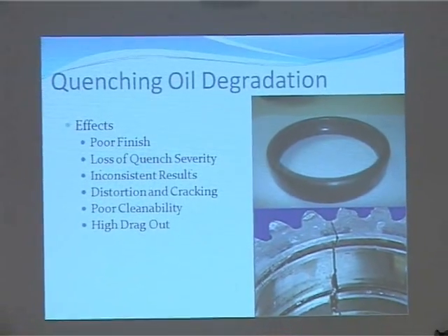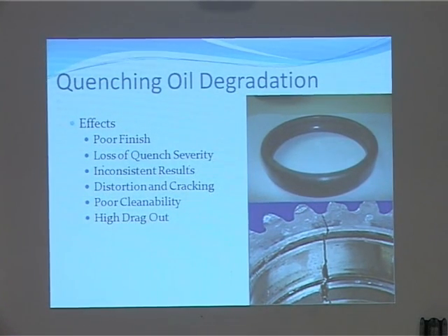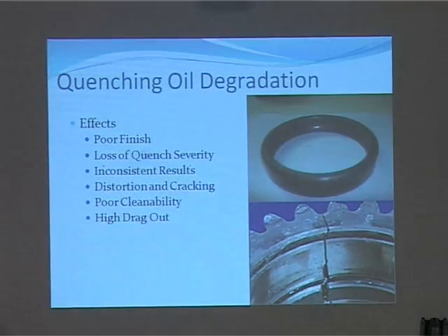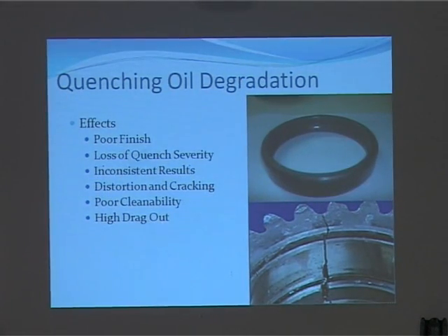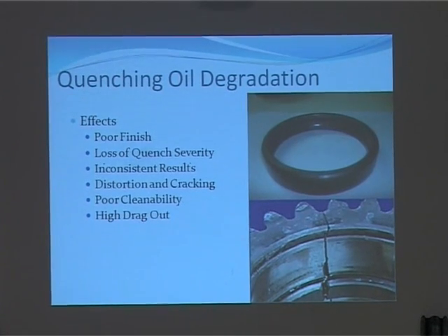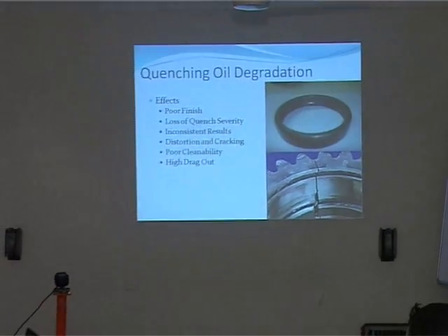Similarly, for the quenchant media, if you are still using oil that does not pass those criteria, the effects will be that the finish will not be good, the quenching severity will not be good, and there will be inconsistent results. You will not get the desired result you are looking for. Then distortion and cracking start.